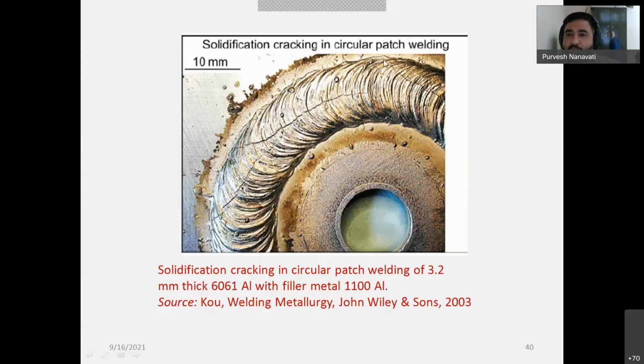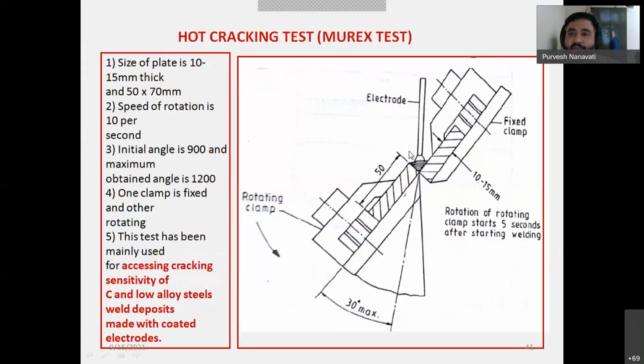आप crack देख सकते हैं, right? You could see a crack, and at a scale of 10 mm, you literally see a large crack of centimeter size, right? This is a solidification crack in circular patch welding, right? Now this is a figure with 1100 filler on a circular patch weld of 3.2 mm thick 6061 aluminum with filler metal 1100. So this base metal was 6061, an aluminum silicon magnesium alloy, and 1100 is the filler, right? Another case is a hot cracking test or Murex test.